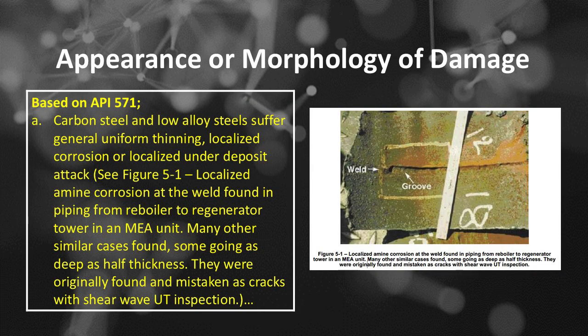Amine corrosion appearance or morphology of damage, based on API 571. A: Carbon steel and low alloy steels suffer general uniform thinning, localized corrosion, or localized under-deposit attack. See Figure 5.1, localized amine corrosion at the weld found in piping from reboiler to regenerator tower in an MEA unit. Many other similar cases found, some going as deep as half thickness.